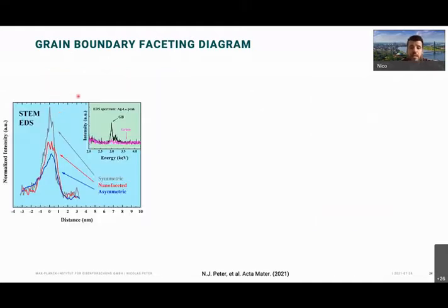We characterize now our silver inside the grain boundary with EDS, and that has a certain reason, because with APT, you cut out a needle, you don't really know where you are in depth. That's pretty hard to determine. If we just cut a cross section and look at it in TEM, we can locally be very precise where we measure our concentration. And very precise means at atomic resolution.